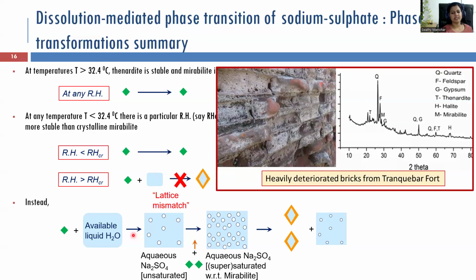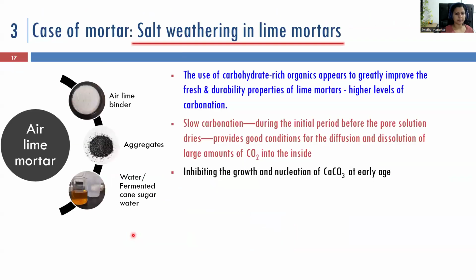Even though this is our theory, this has been experimentally observed and investigated in one of our case studies, which we did in a brick fort wall in Tranquebar in Tamil Nadu, which was severely damaged because it was directly exposed in the seashore with marine conditions and very high relative humidity.